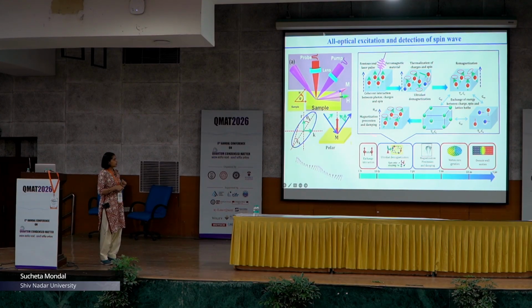If there is an external magnetic field present, or an internal magnetic field in the form of an anisotropy field present in the sample, the spins will relax, as well as experience a torque which will make them precess. This precession has 2 components, one is frequency, another is damping. So, damping is of course obvious. Damping will also be calculated from the envelope of the dying signal which we get in the time resolved spectra. So, the typical timeline of this phenomenon is, like I mentioned, from femtosecond to nanosecond.